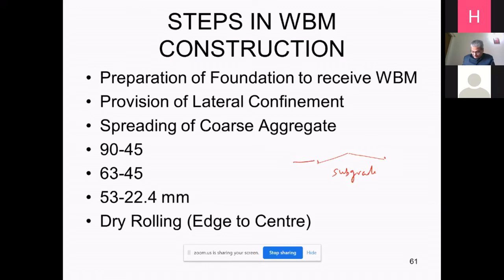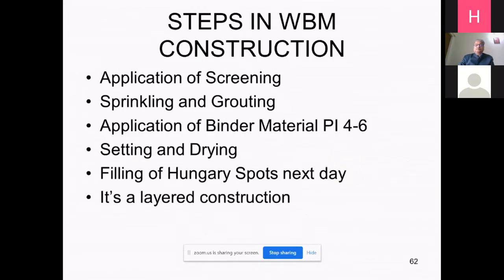Then lateral confinement means shoulders are to be made first. Then spreading of coarse aggregate. Then dry rolling from edge to center. Rolling is always to be made from the sides to the center, not from center to the side. If you are making it from center to the side, then camber will vanish. Camber will not be there. So always start rolling from the sides toward the center. Then application of screening, as I said.